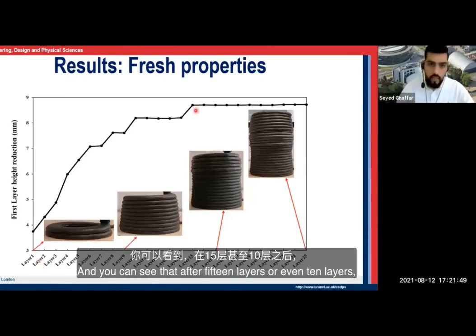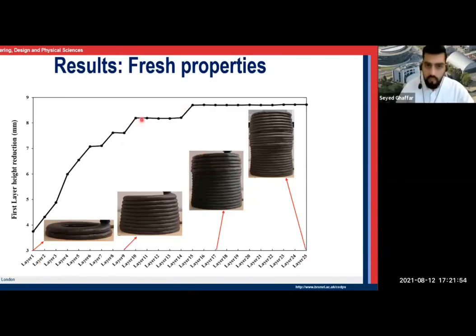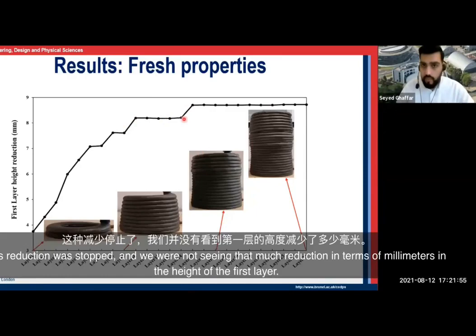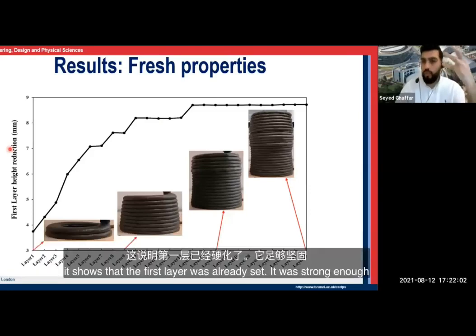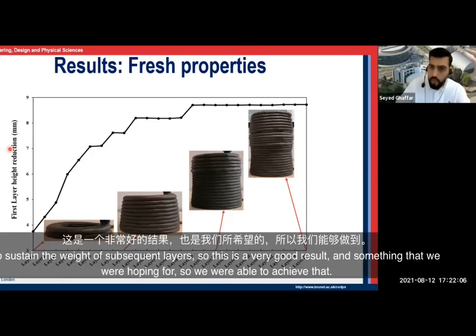And you can see that after 15 layers or even 10 layers, this reduction stopped, and we were not seeing that much reduction in millimeters in the height of the first layer. It shows that the first layer was already set. It was strong enough to sustain the weight of subsequent layers. So this is a very good result and something that we were hoping for. So we were able to achieve that.